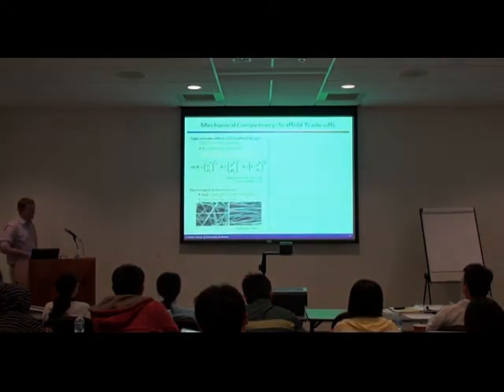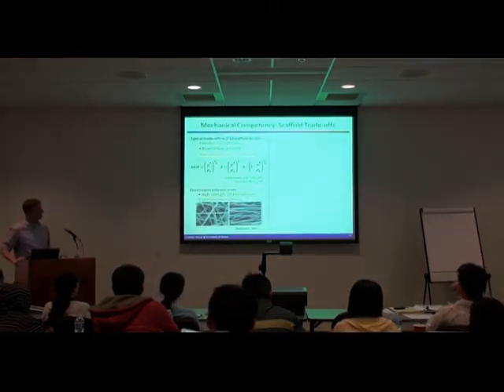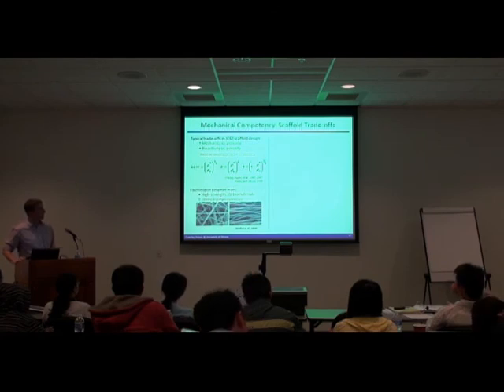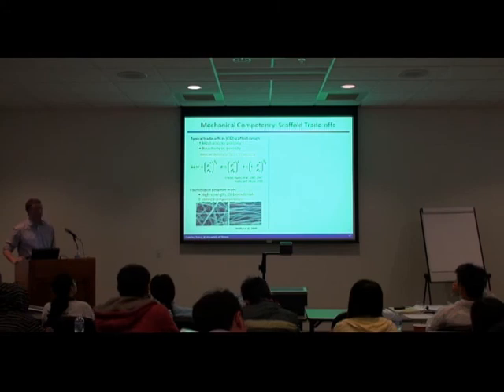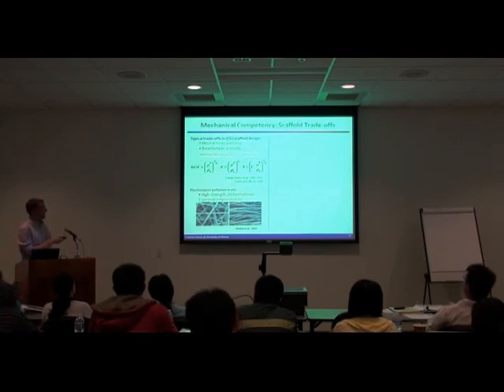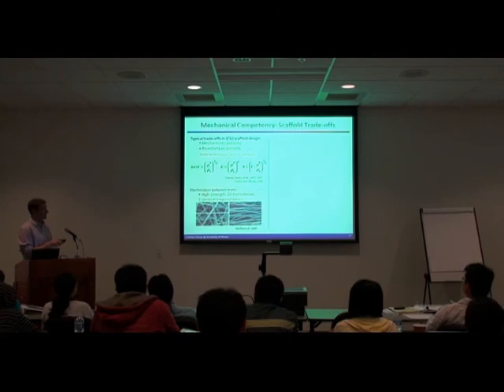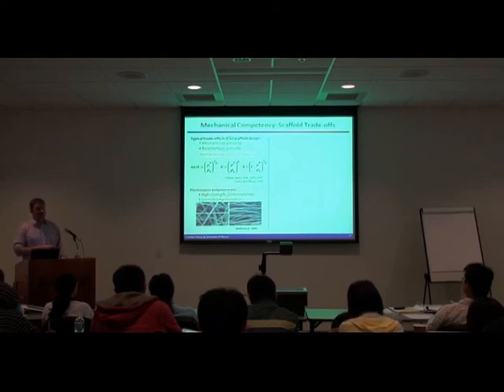Now, the most interesting aspect, and where we went back to this idea of understanding relationships between microstructure and mechanical properties, is how you design materials to be strong in tension when they're porous. There's the classic problem that tissue engineering has had, where mechanics and porosity are very much related. We talked a little bit about the modeling framework, where the modulus of the scaffold scales with relative density squared. So as the scaffold becomes more and more porous, it becomes less and less stiff.